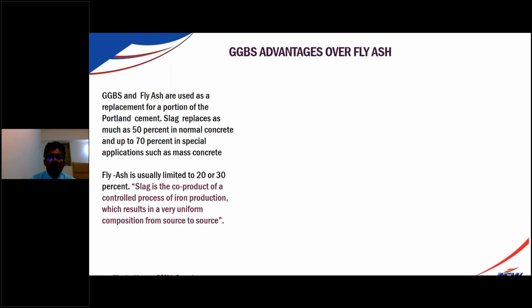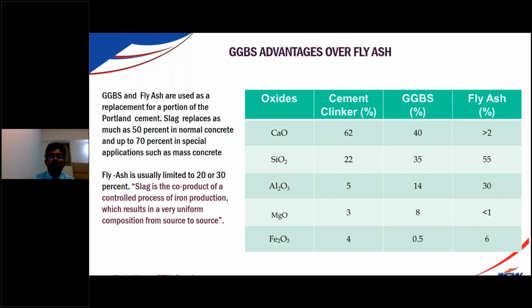So people will always compare with fly ash. They say, I will use fly ash, I will not use GGBS. I am not working against fly ash, but what I am telling you is that GGBS is a superior product compared to fly ash because it is both hydraulic and pozzolanic. The reason behind it is the chemical composition. We have 40% calcium oxide compared to OPC clinker 62%, silicon dioxide 35% whereas cement has 22%, aluminum oxide 14%, clinker having 5%.